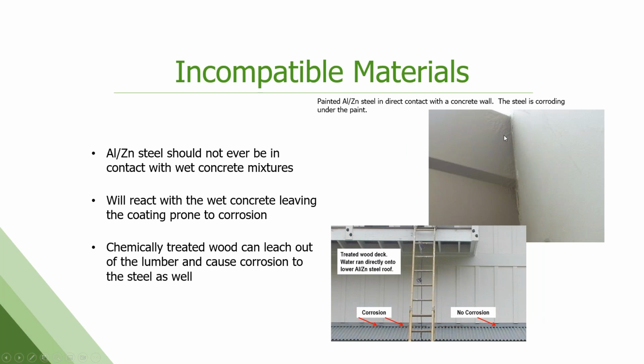Concrete: pouring wet concrete up against these panels without a barrier, you're going to get moisture intrusion and cause corrosion. Again, it causes the paint to bubble off and peel. Chemically treated wood, which often has copper compounds in it, which pre-painted metal doesn't like, can be an issue. This is a house on Maui. Corrosion was occurring underneath this upper deck only. We found out that the wood was copper treated, so it's leaching out as rain falls onto the roof below. Once you get out past this deck over here, no issue with the metal at all.